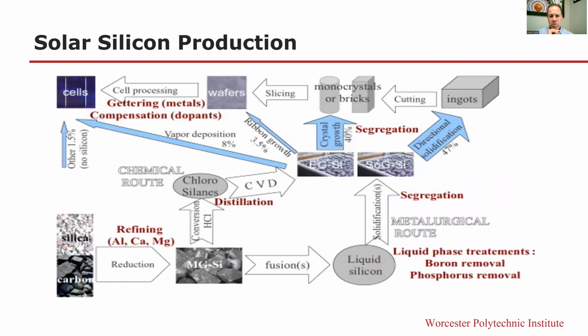And in order to do that, we need to first back up and look at the overall flow sheet of solar silicon production. It's a relatively complex process, beginning with carbothermic reduction of silicon dioxide to metallurgical grade silicon. This dramatically reduces the purity. It adds a considerable amount of impurities from the carbon material. So then we spend quite a bit of energy and effort to remove those impurities by conversion to chlorosilane, and then distillation, followed by chemical vapor deposition, a very intensive process.